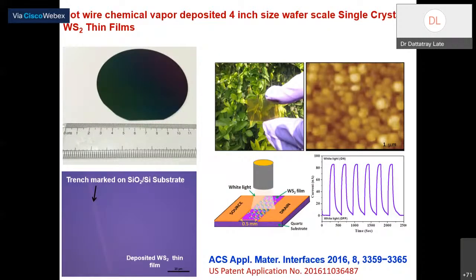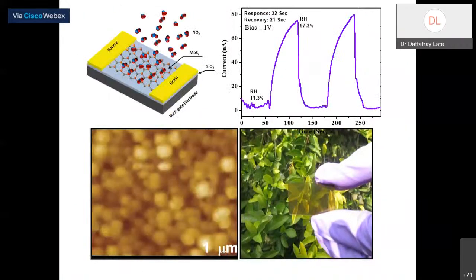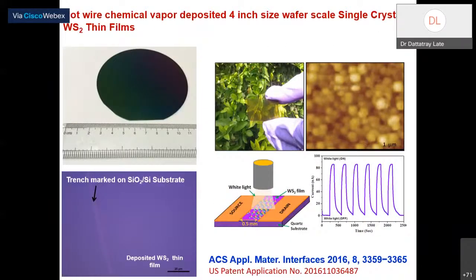Again, I have another method here, which is known as hot wire chemical vapor deposition. So hot wire means here I have a vacuum chamber. Suppose I want to deposit a WS2 film. I need a tungsten wire or high-melting-point metal wire or electrode. And in that chamber, I will heat the tungsten wire up to evaporation temperature. What is the evaporation temperature of tungsten? Tungsten evaporation temperature is more than 2000 degrees Celsius. I will evaporate the tungsten at that temperature and I will pass the sulfur gas.